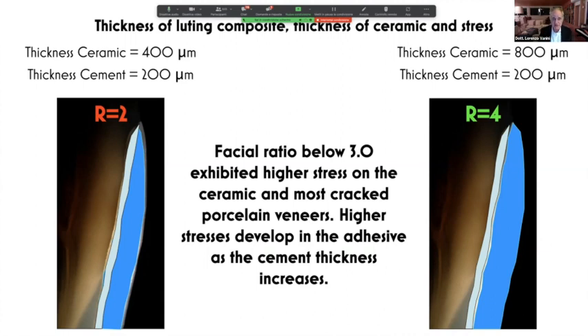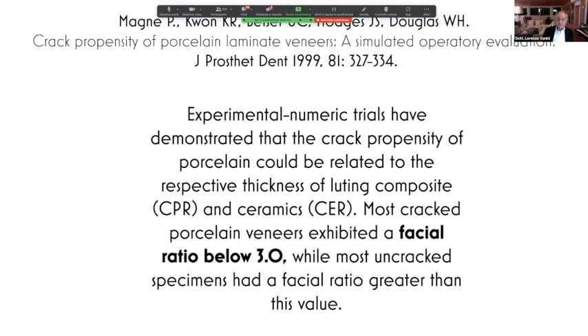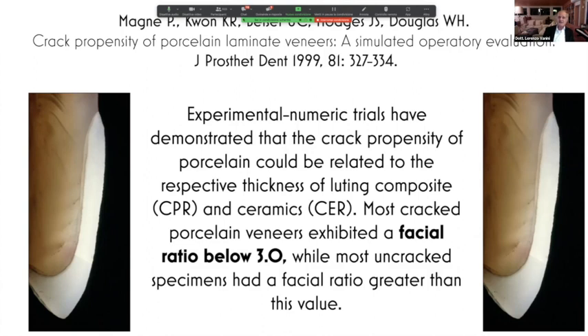It's important also the ratio between the thickness of the ceramic and the thickness of the cement. A facial ratio below 3 is not good. We have to stay above 3, for example 4, in this relationship between the thickness of the cement and the thickness of the laminate. And we know that experimental numeric trials have demonstrated that the crack propensity of porcelain could be related to the respective thickness of luting composite and ceramics. Most cracked porcelain veneers exhibit a facial ratio below 3.0, while most uncracked specimens had a facial ratio greater than this value. So it's important to have this relationship between the thickness of the ceramic veneering and the thickness of the cement.